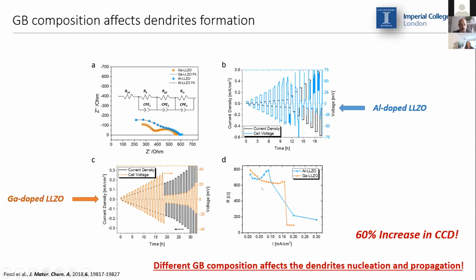Some samples were gallium doped. So we've seen that even in the gallium doped, we do have a tiny amount of aluminum that segregates at grain boundaries. But then we compare the gallium doped with aluminum doped samples. So in the aluminum doped sample, we replaced completely the gallium with aluminum. So we are expecting to have a lot of aluminum at the grain boundaries.